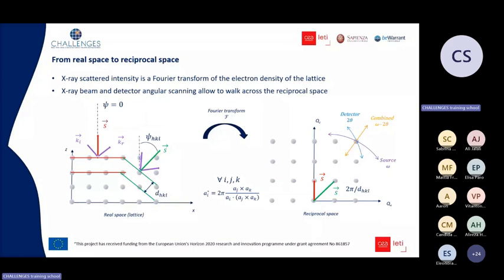So diffraction can be seen here simply by a Fourier transform. So we start from the electron density of the lattice, and diffraction is just mathematically a Fourier transform. So we go from the direct space to the reciprocal space here by just a simple conversion, and by moving the incoming beam and the diffracted beam, you can just walk through this space. And so by determining the distance or the position in the reciprocal space, you can go back to the real space and calculate the strain, the lattice parameters, and then the strain.